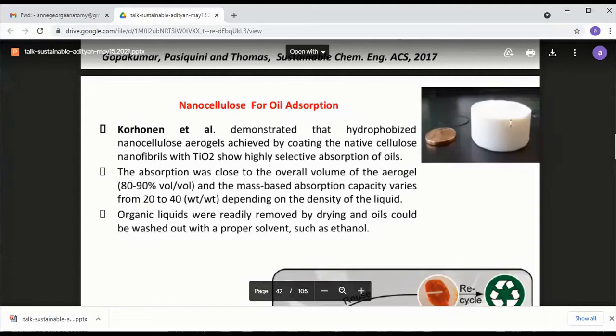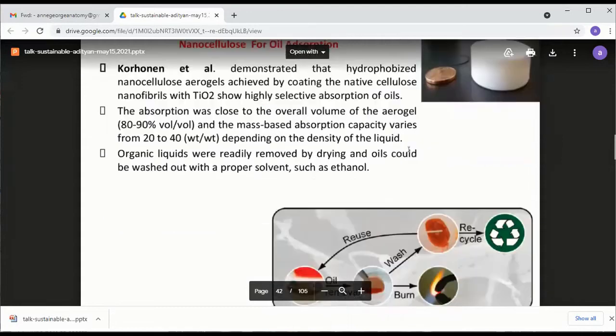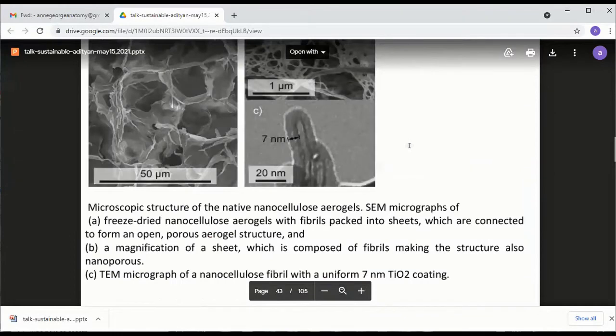They made use of nanocellulose. Look at this picture. They made nanocellulose aerogels, lightweight aerogel. Manufacturing is very simple. You disperse nanocellulose in water and go for freeze drying. You can make this sort of foam-like structure. But the Finnish group did some interesting chemistry. Look at this. The Finnish group did a coating on the surface of this nanocellulose using TiO2. This is a TiO2 coating. 7 nanometer coating they gave. You know why they did that? To make the surface hydrophobic.